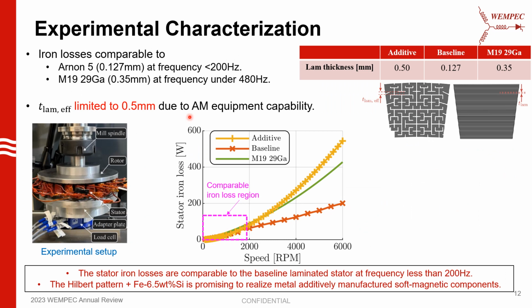The iron losses in the stators were measured using a no-load test. The minimum feature size of 0.5 mm in the 3D printed stator translates to an effective lamination thickness of 0.5 mm. This is the thickness of each of these features. The baseline stator used 0.127 mm thick Arnon 5 laminations. So we also compared the iron losses of these two stators with a 3D FEA solve performed using M19 29 gauge, which has 0.35 mm thick laminations that is comparable to the additive stator. The iron loss values are plotted here across the speed range of operation of this machine.